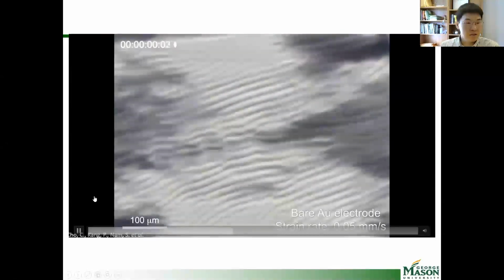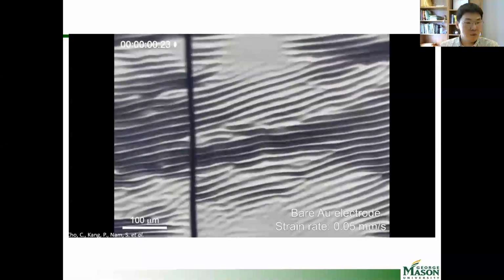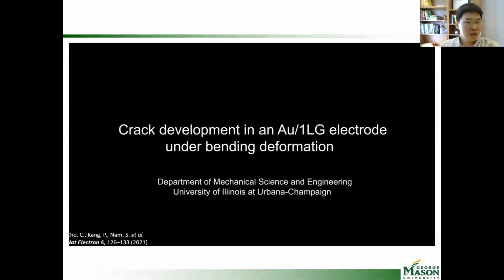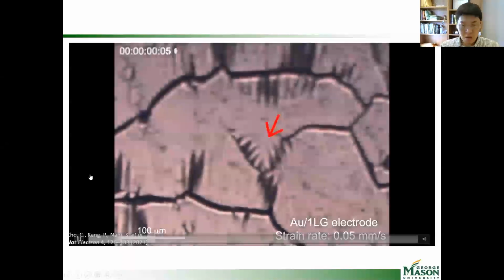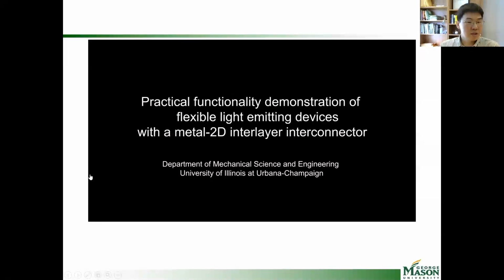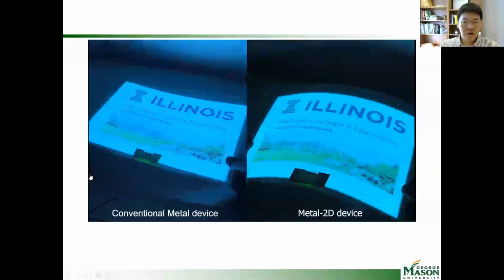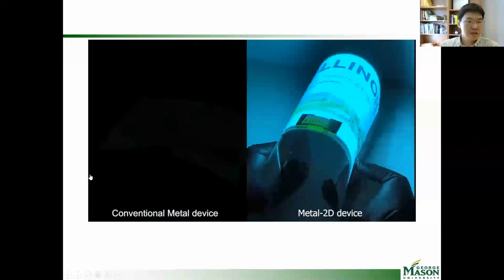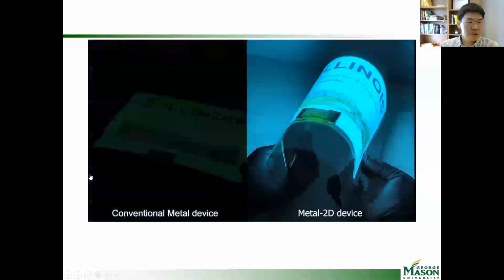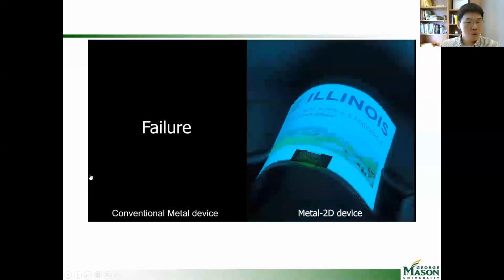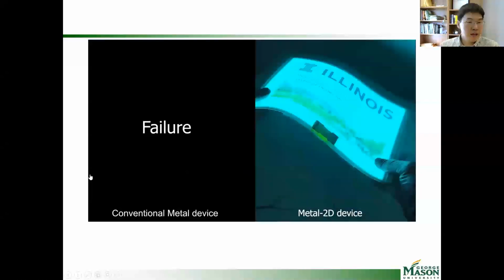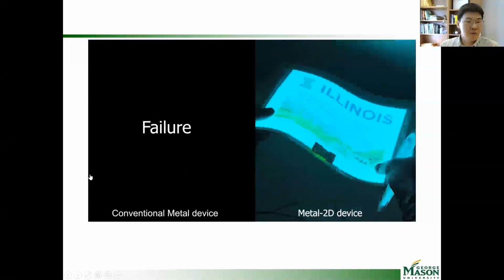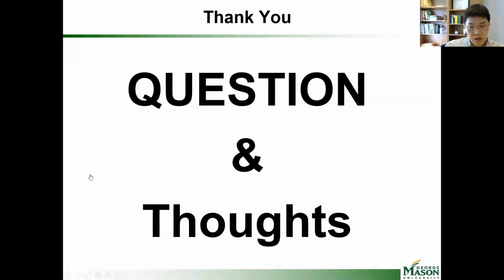So this shows how we can modulate the fracture mode, and using these physical mechanisms of modulating the fracture mode, we use this as a universal tool to enhance the electrical properties and mechanical robustness of the film. So we integrated our approach with these flexible displays so that we can enhance the mechanical robustness of these flexible displays. So with that, I'd like to just stop here.